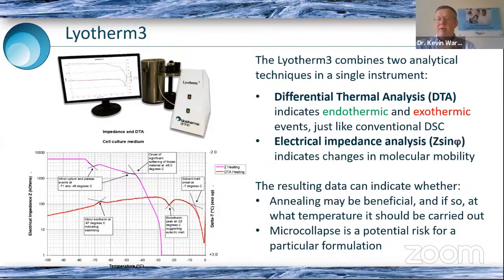And so a good example of this is if we put mannitol into a formulation, which when it crystallizes has a very high eutectic temperature, but say we have glucose in our formulation, which we know will collapse somewhere around -40 or slightly below, then if we process them at a temperature which is between those two critical temperatures, so say -20, we might expect the mannitol to be fine, but we might expect the glucose to collapse.